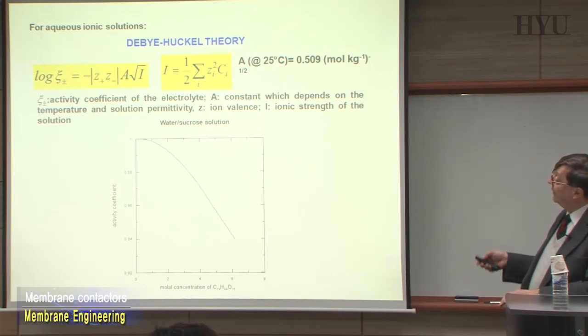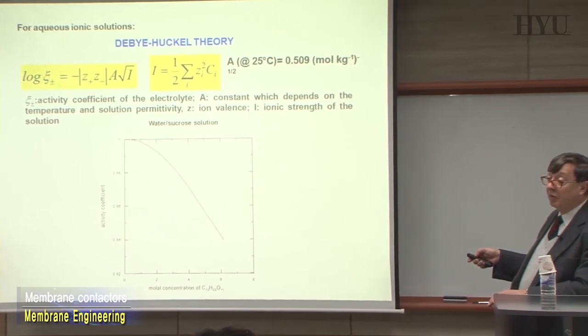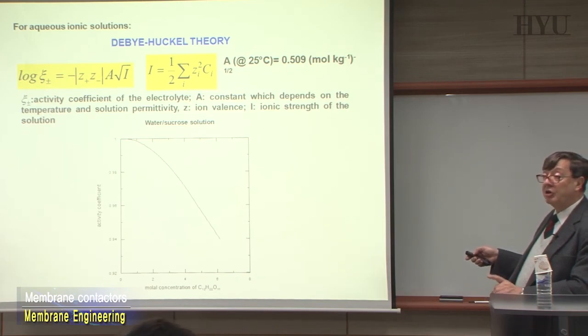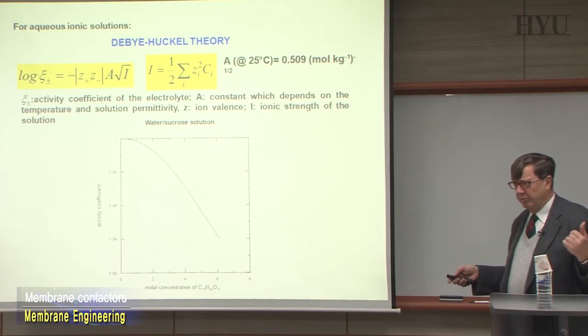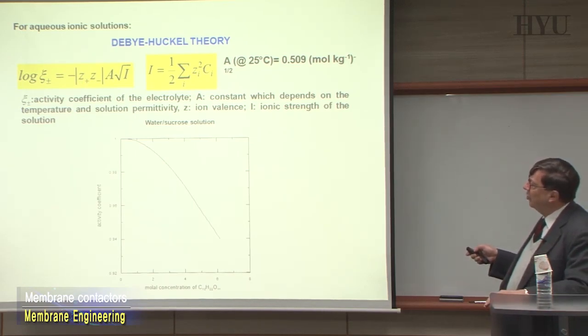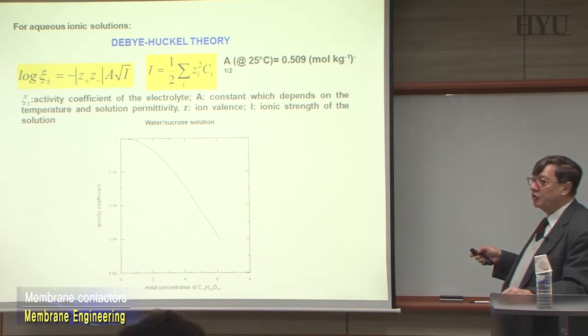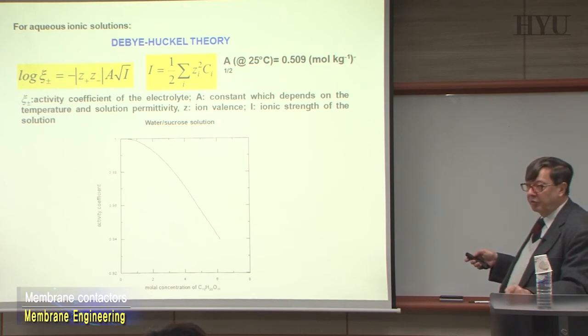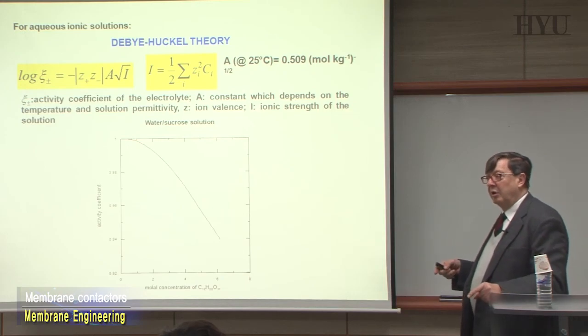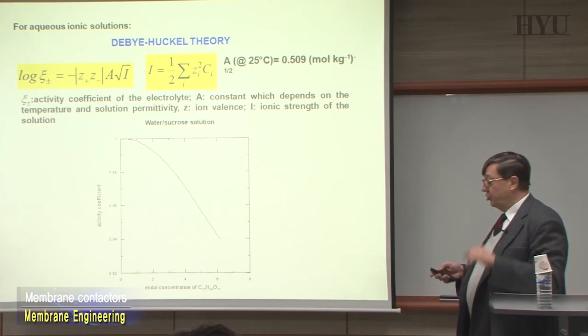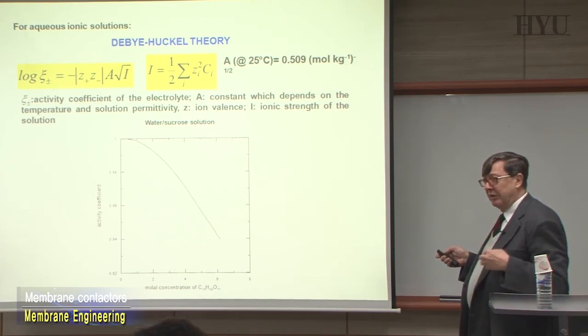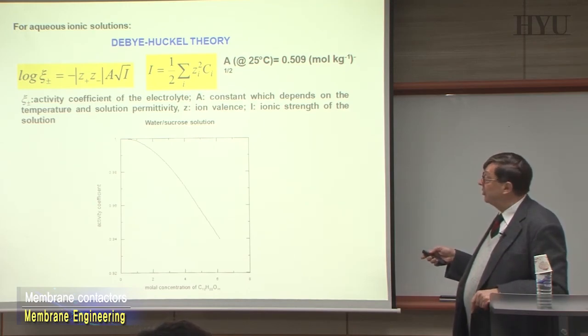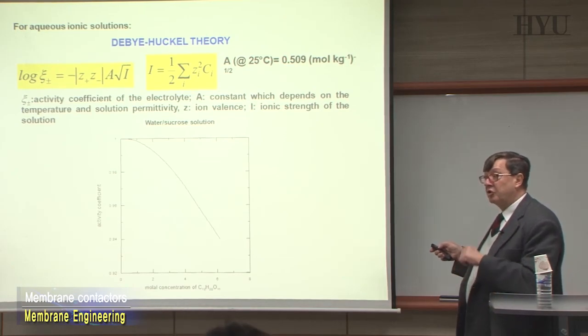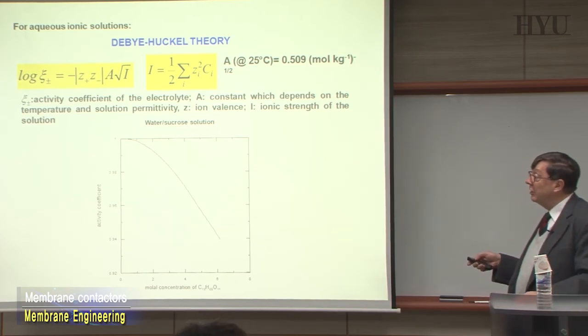For doing this, you find the relationship is interesting, where you can introduce the activity coefficients that we have mentioned before, related to what is called the ionic strength of your solution. I already mentioned this when we spoke about the Donnan effect, etc. The ionic strength of the solution is nothing more than the sum, over all the different ions, of the concentration multiplied by the square of the charge of the single ions. So this is the overall ionic strength of your solution. If you have a monovalent salt or a bivalent ion, etc., the ionic strength is changing. So it does not change only the molar concentration, but the real deviation from ideal character that you measure through the activity coefficient is changing as a function of the product of the molar concentration and the square of the charge of the single ions. And that makes a difference in the deviation from ideal character.